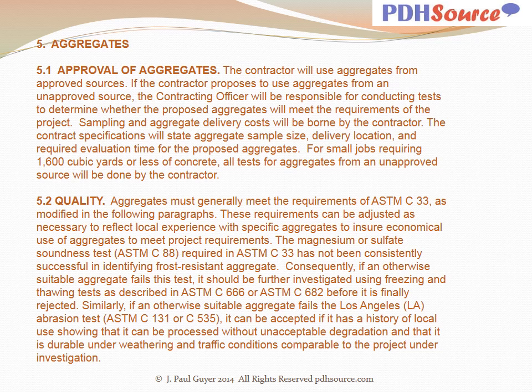Aggregates must generally meet the requirements of ASTM C33. These requirements can be adjusted as necessary to reflect local experience with specific aggregates to ensure economical use of aggregates to meet project requirements. The magnesium or sulfate soundness test, ASTM C88, required in ASTM C33, has not been consistently successful in identifying frost-resistant aggregate. Consequently, if an otherwise suitable aggregate fails this test, it should be further investigated using freezing and thawing tests as described in ASTM C666 or ASTM C682 before it is finally rejected.